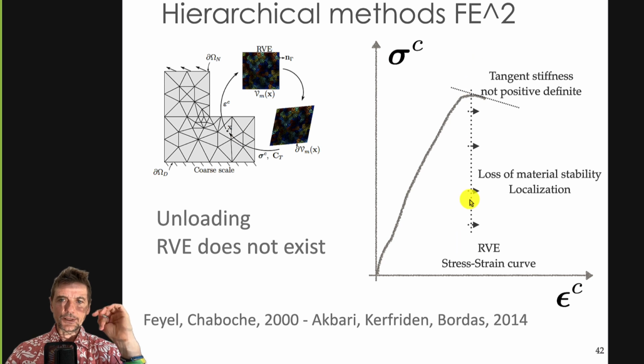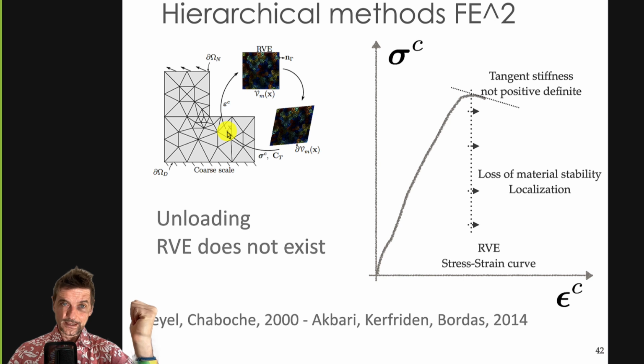Because if you don't do anything, when you have this localization, you will have localization of strains. And if you don't do anything, this element will damage, and unfortunately, your results will be mesh dependent. Because if you refine the mesh, the element will also damage, but now it will be a smaller element, and therefore you will localize in a smaller element. If you refine the mesh again, you will localize in yet a smaller element, until the element size goes to 0, and the localization happens in a set of measure 0, an element which is infinitely small, and therefore the energy that you dissipate is now 0. So you dissipate no energy, which is contrary to physics.